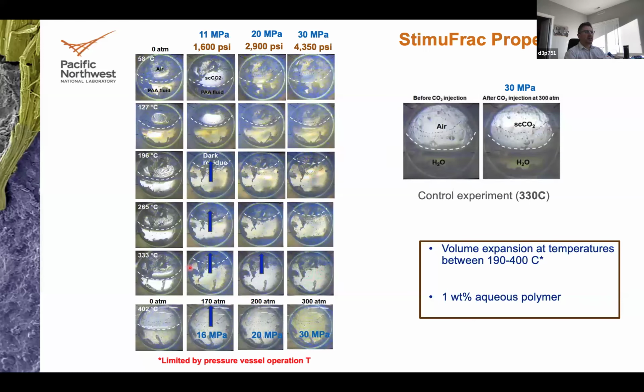This expansion, like I say, is an exothermic reaction, so temperature triggers higher and higher volume expansion and higher changes in viscosity. And what we see, for example, at 400 Celsius, if you want to go super hot, at 400, 450, 475, or 500 Celsius, I believe we can get expansions at as low as 1600 psi and changes obviously in viscosity. So this fluid expands at lower pressure of CO2 as you have higher temperatures in the cell.